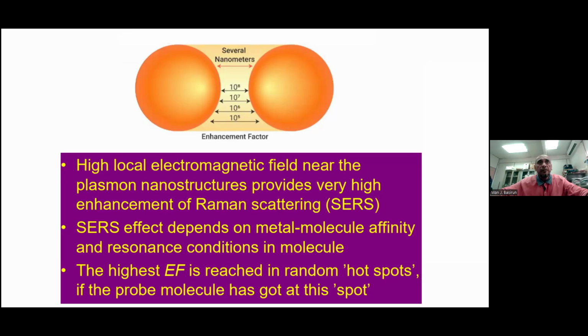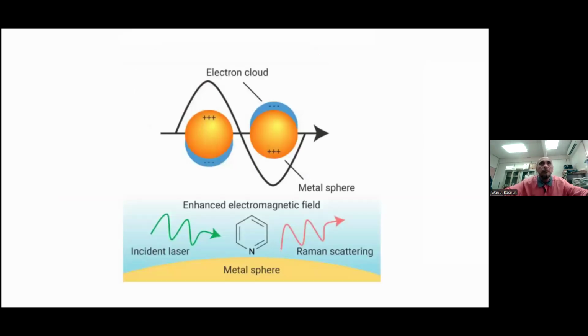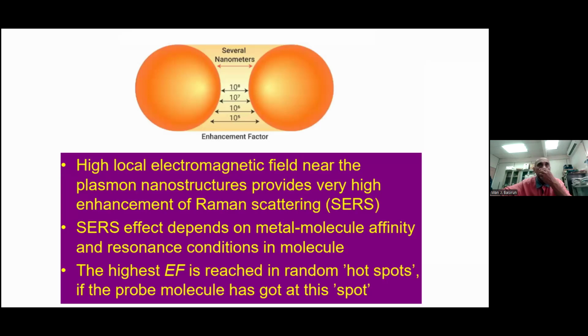So this SERS effect depends on the metal molecule affinity and the resonance condition, and the highest electromagnetic factor is reached at random hotspot. So, for example, once you have this effect, this nitrogen or the pyridine molecule which is bonded with the metal surface, this is the hotspot. This hotspot contains very large enhancement, due to the electromagnetic. So that's why we call it hotspot. So the region between the nitrogen or the pyridine molecule and the gold surface, this is a hotspot. And this hotspot is very critical in Raman detection of the molecule itself. Okay, so this is the best explained effect of the electromagnetic enhancement.